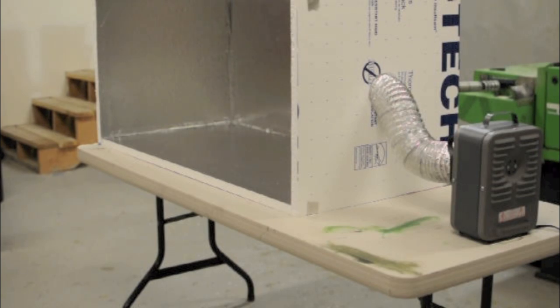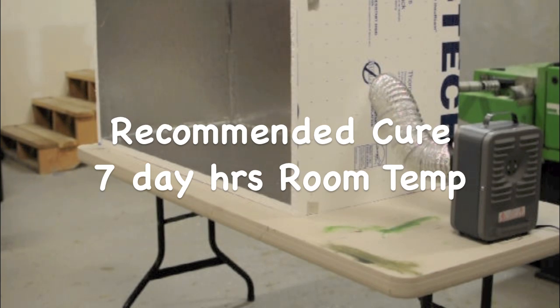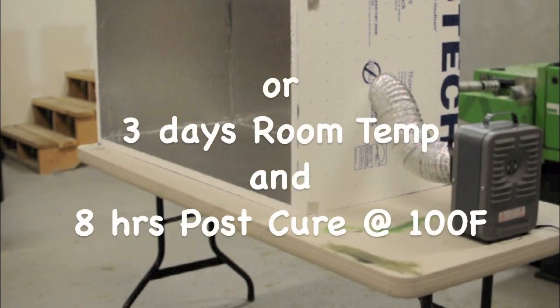One of the few drawbacks to using epoxy as opposed to other resins for castings is the long cure cycle. Our casting resins require a 7-day room temperature cure prior to demolding, or a 3-day room temperature cure with an 8-hour 100 degree Fahrenheit post-cure.